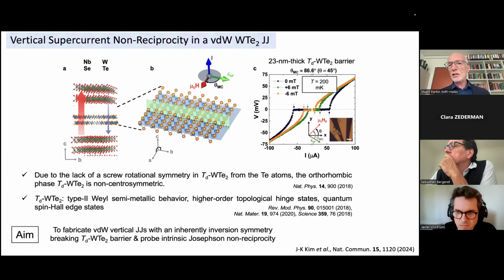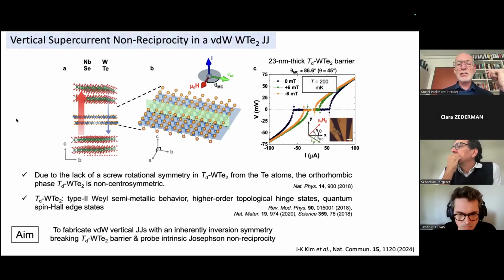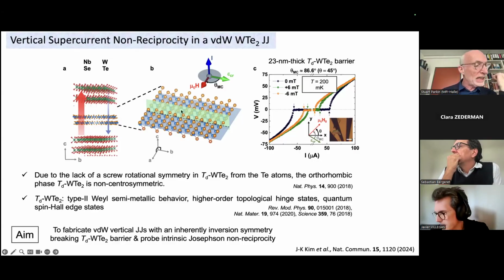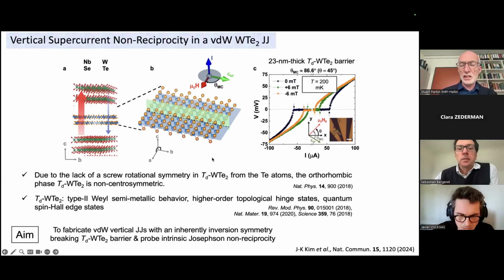And tungsten ditelluride is a super interesting material for all sorts of reasons, but in particular, it has an orthorhombic structure. And this is very important. So it's a non-centrosymmetric material, and the green plane is a mirror plane that this structure persists. So now what we're going to do is we're going to look at the voltage current characteristics in the presence of a magnetic field.